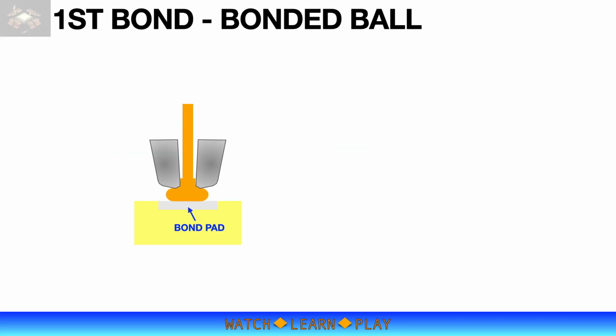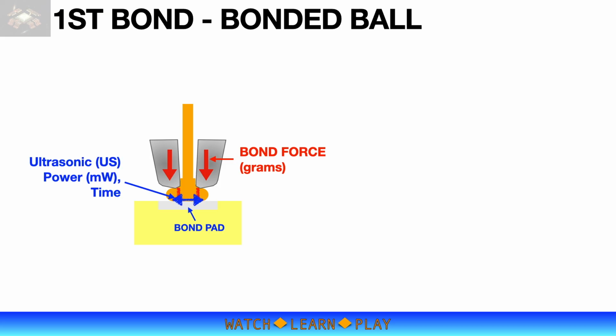First bond is the bonding of the free air ball to the bond pad. A bond pad is a small area of thin layer of aluminum. First bond requires a small amount of force to press the free air ball onto the bond pad, followed by ultrasonic power to form the bond between two materials. The bond is a very thin gold-aluminum intermetallic layer, and the strength of the bond depends on the amount of intermetallic formed.